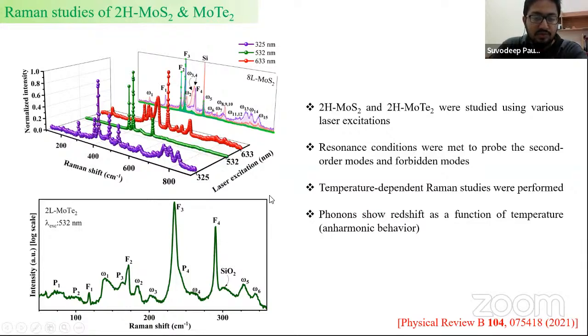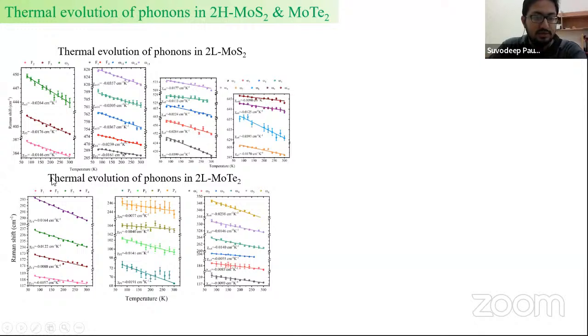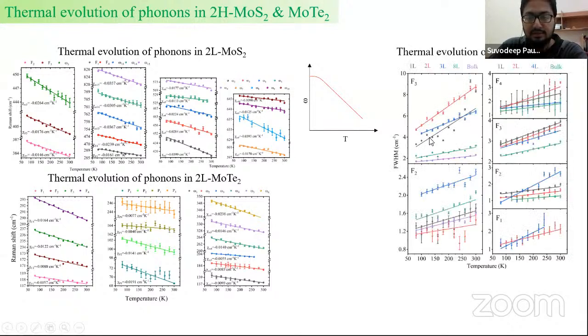And we performed temperature dependent experiments, which gave us some data which looks like this. All of the modes we see show a red shift as a function of temperature, which is what we would expect from the anharmonic theory. And on the other hand, the line widths show an increase with increase in temperature. That's also consistent with the anharmonic theory.